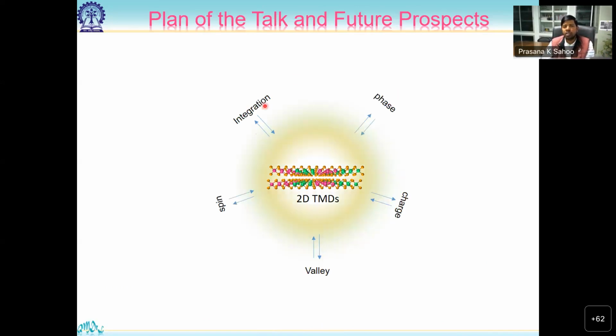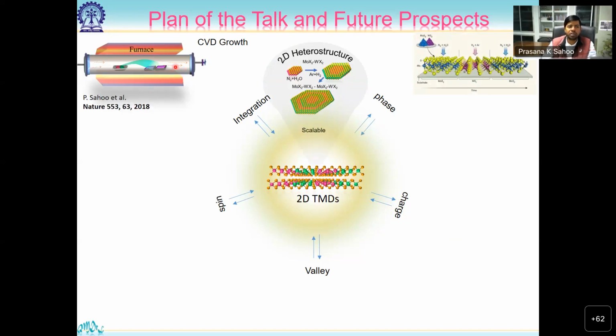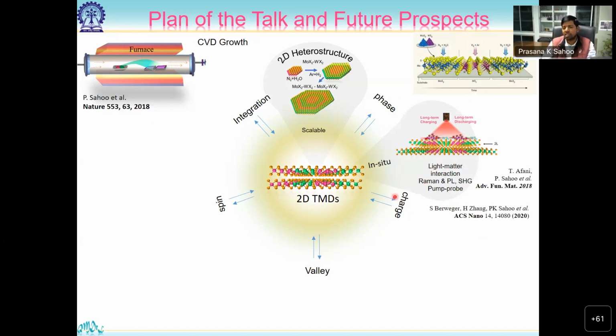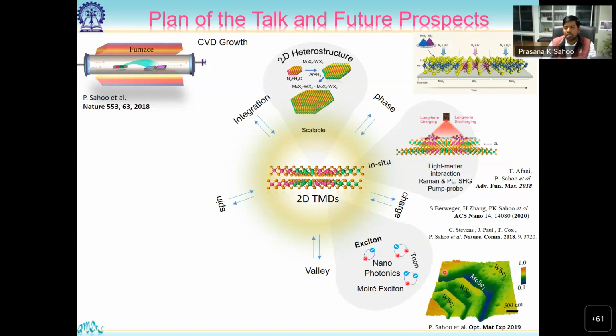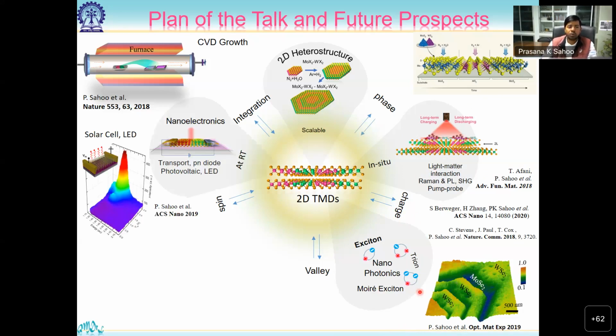So I think this is what we developed, a method where we can systematically grow this kind of high-quality crystal using CVD, chemical vapor deposition, where we can grow these lateral structures side by side. We can grow MoS2, then on the side WS2, again on the MoS2. So we can grow this kind of structure directly by the CVD method. In this kind of structure, we showed very strong light-matter interaction characteristics. Also, there are very interesting exciton-based domains one can realize in photoluminescence mapping. Also, we demonstrated nanoelectronics like a small PN junction diode, photovoltaic, and light-emitting diode using these atomically thin samples.